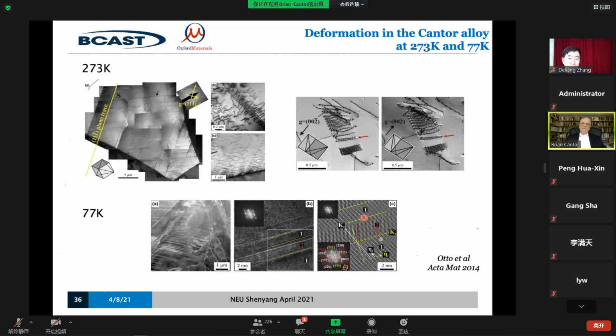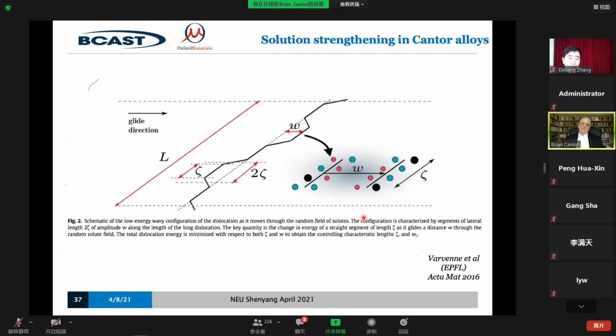But the strength is very high for an FCC material. It's not like FCC copper and FCC gold. And the reason is these small local environments being so different. So here's a dislocation line. Sorry, this black line is the dislocation line. And it has to move through different local environments. These are not meant to be different atoms. They're really meant to be different local environments. So the dislocation becomes very organized like this, and as it moves, it's got to judder forwards to get through the local strains. And that is what dominates the deformation behavior.